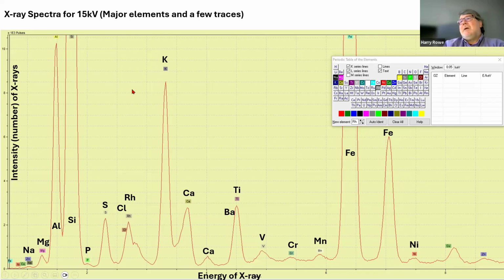In general, this is the 15 kV setting, so that we can measure from sodium all the way up to about iron. There's a couple of trace metals here that we have, but sodium is a very small peak here. We need to be able to measure that, so we measure it now for about 5 seconds. Used to be that we measured it for 3 minutes. That was 15, 16 years ago, but now in 5 seconds we can get a good analysis on that sodium, magnesium. But we need all this to be clean and make sure that we're measuring the rock.